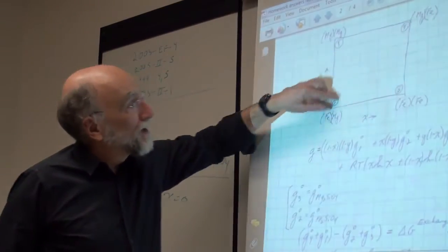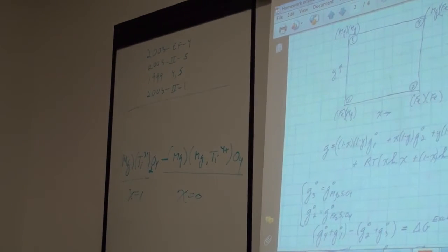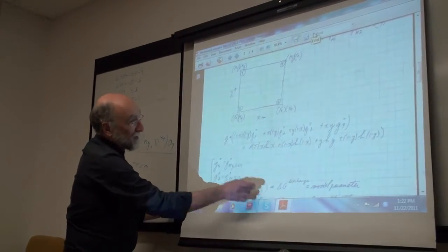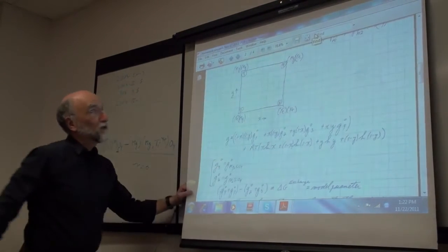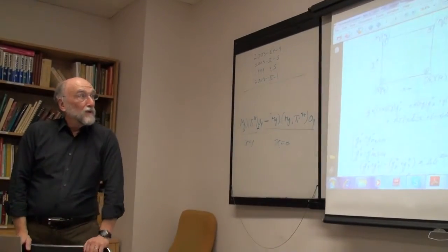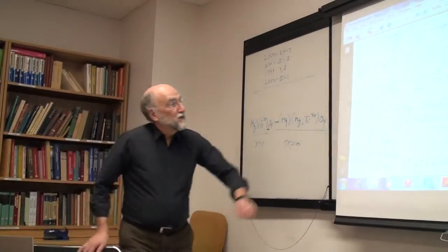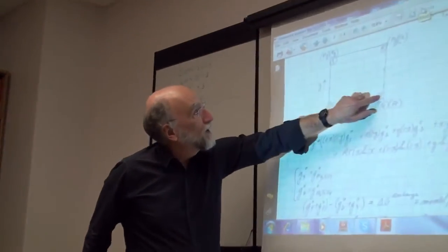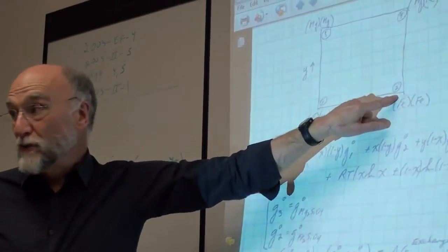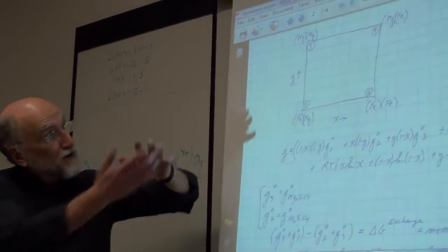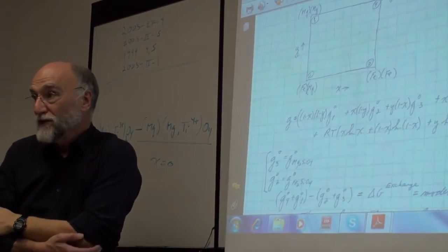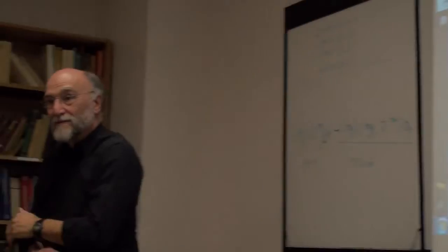You can't choose one of these arbitrarily. All four formalism parameters have a meaning. But this thing and the difference between G4 and G1 are actually two model parameters that physically determine what's going on. So if you make this more negative than this, it'll tend to go this way. If you make this more negative than this, it'll tend to go this way. But at the same time, this sum here is going to tend to give you a tendency to demixing or not.